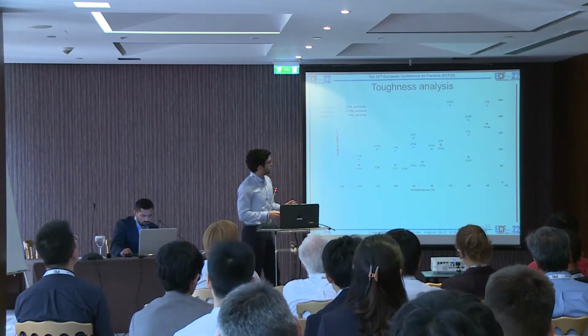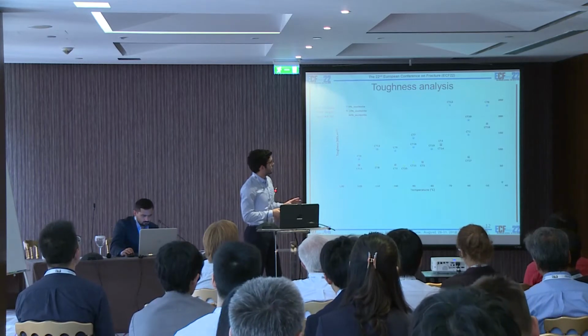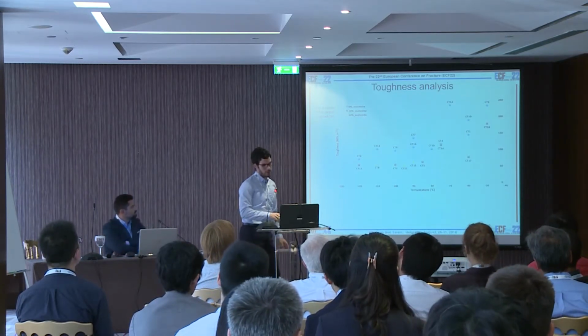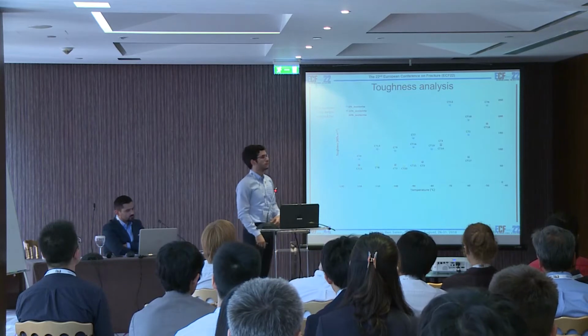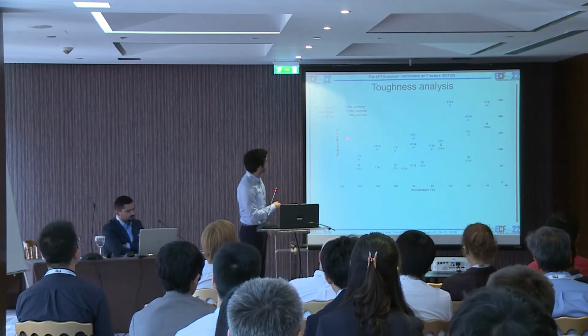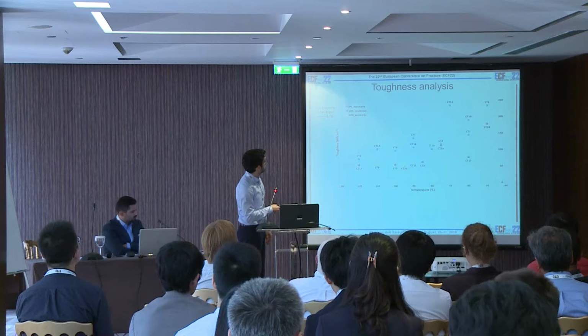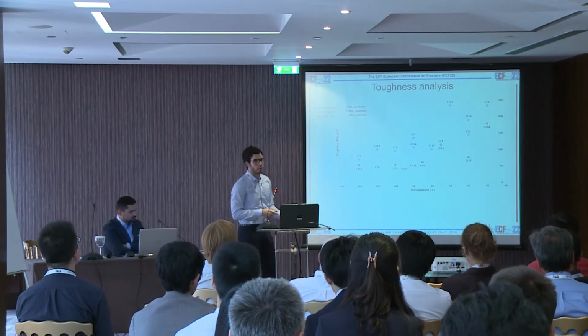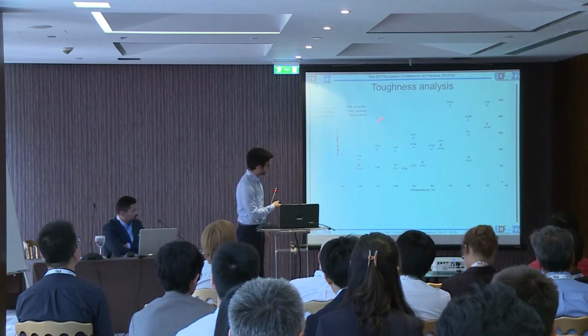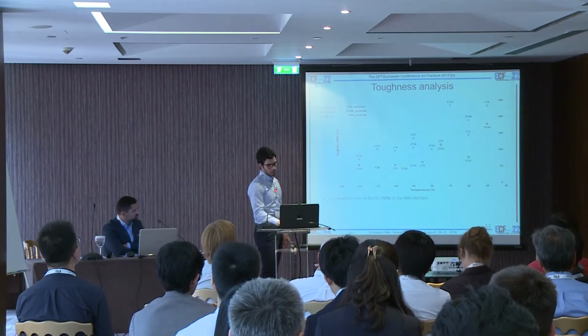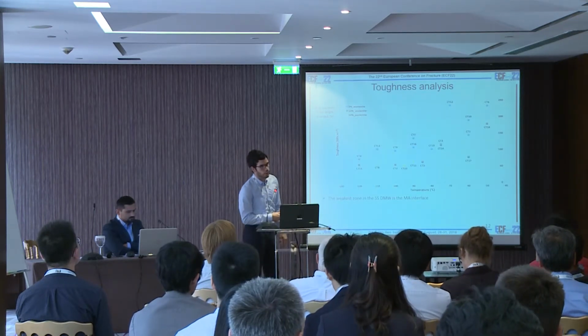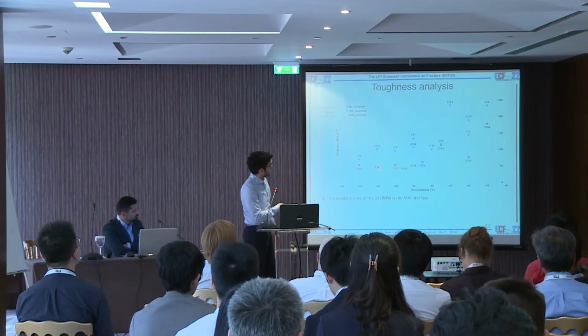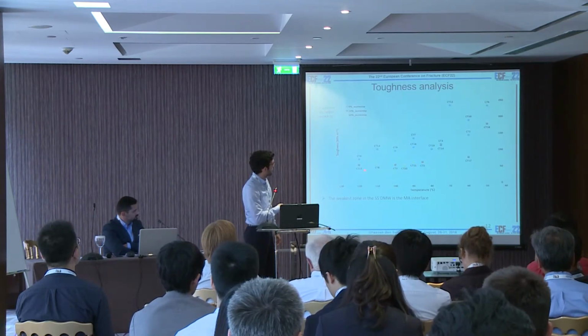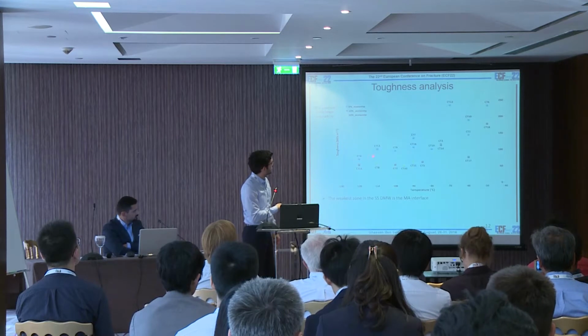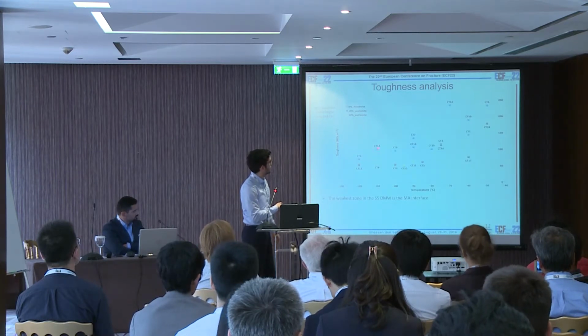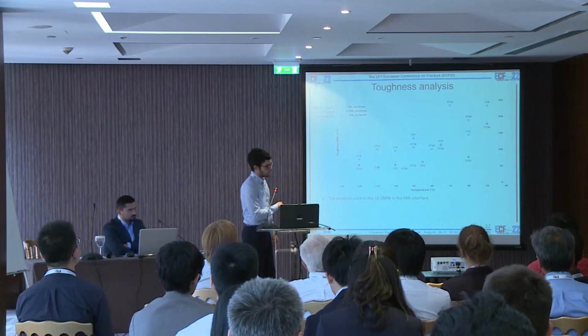So now that we have shown the role played by the presence of austenite in the fatigue pre-crack, we can take the toughness values analysis one step further, and we can sort the different specimens based on the proportion of austenite in the fatigue pre-crack. That's what we see here, the different values. And we can see that there is a clear disparity between specimens who have austenite in the fatigue pre-crack, so red and green, and specimens with only ferritic steel in the fatigue pre-crack in blue.